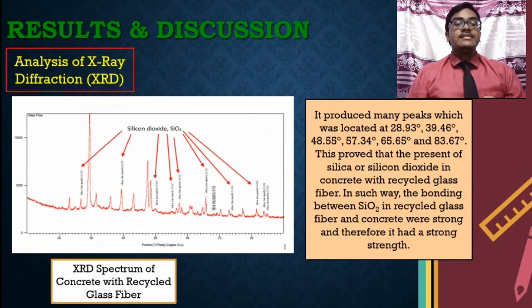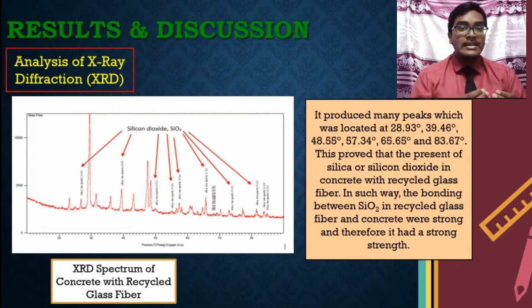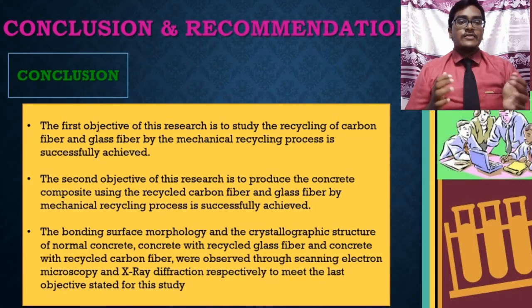In addition, the figure shows the XRD spectrum for concrete with recycled glass fiber. It produced many peaks. Okay, this proves the presence of silica or silicon dioxide in concrete with recycled glass fiber. In this way, the bonding between silicon dioxide in recycled glass fiber and concrete was strong, and therefore it has strong strength. Okay, now we're moving to the conclusion.